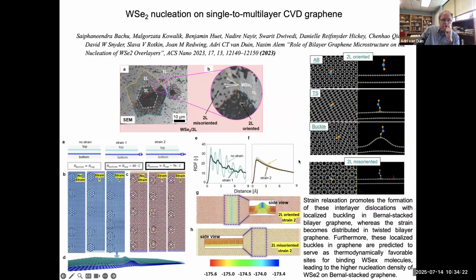Graphene is a very popular growth material. We found, very interestingly, that if you grow on a bilayer of material, then the bilayer orientation is a big deal. Whether they're aligned or twisted really changes the way that the 2D material deposits. If they are aligned to each other, we get these sort of local curvatures. If you align them differently, you don't get local high curvature, but you get more small curvatures. These high curvature areas are really nice areas to deposit WSe2, because it prefers to bind to these high curvatures. It doesn't bind very strongly, but strong enough to make an early bond, and that's enough to start your growth.